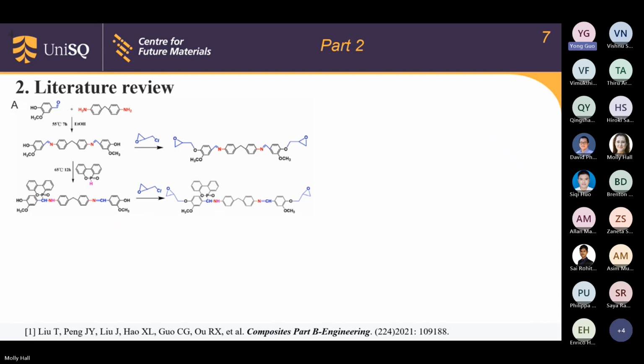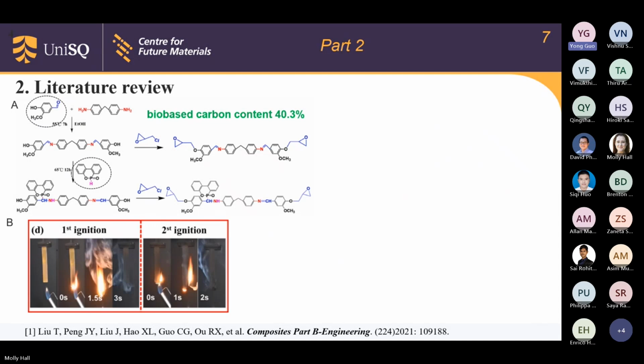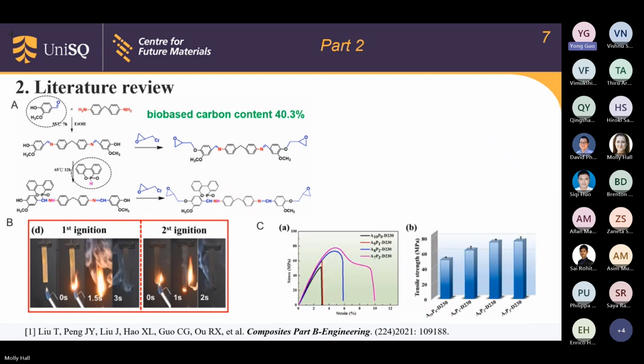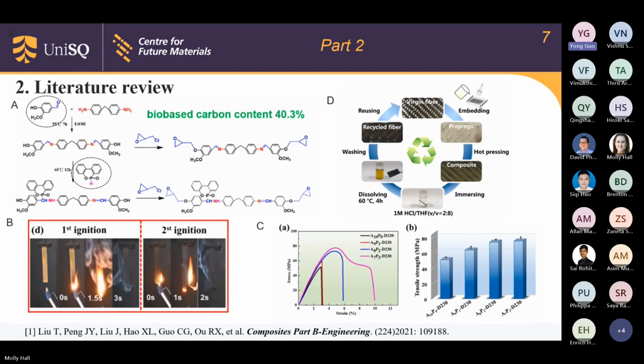Next one, I'd like to introduce the imine exchange. Firstly, the authors used bio-based vanillin to react with an amine, and with the epoxy reaction, to obtain an imine-containing epoxy resin. This system contained a bio-based carbon content of 40.3%. First, it achieved flame retardancy in the UL94 test. Second, it possessed increased mechanical strength compared with the commercial one. Finally, it achieved closed-loop recycling of the CF pieces.